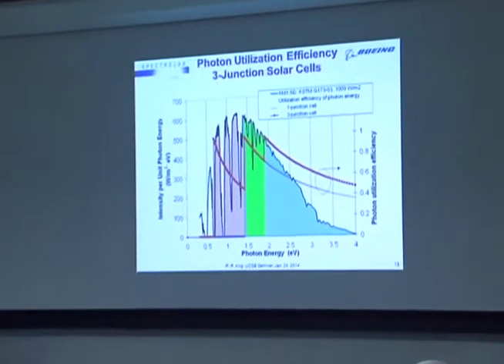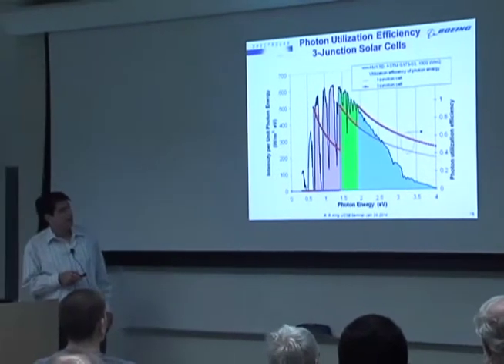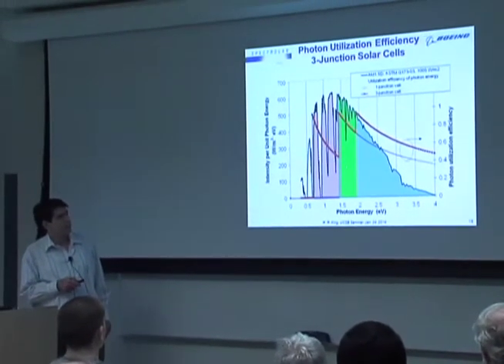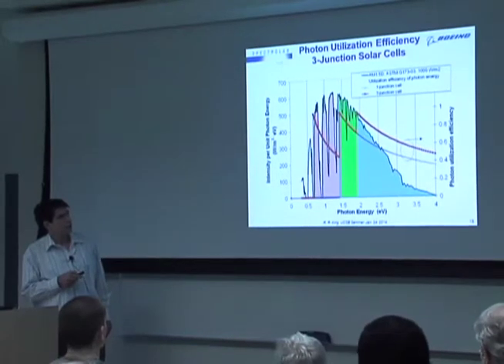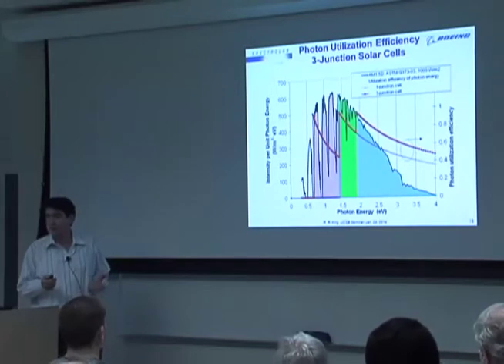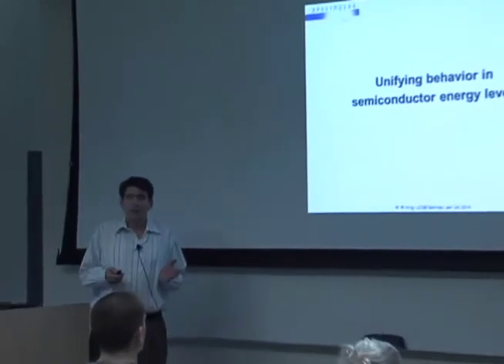And the reason for that, of course, is because we're now using the broad wavelength range of the solar spectrum more efficiently. So we now can use the photons in each of the wavelength ranges of the respective subcells and use much more of the spectrum. So in order to do that, we need to identify subcell materials that have a number of different band gaps. And we need to do those at the same lattice constant, ideally, if we're going to grow a lattice-matched structure. The search for materials of the appropriate band gap at the appropriate lattice constant often leads to a case where we have unwanted defects in the semiconductor materials.